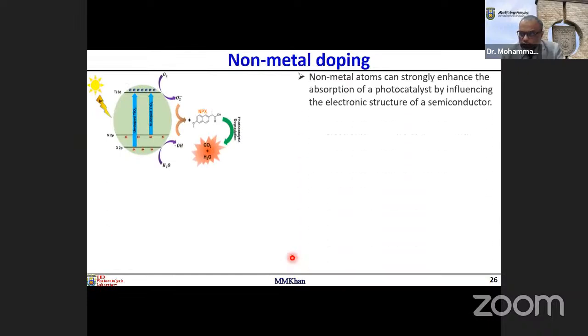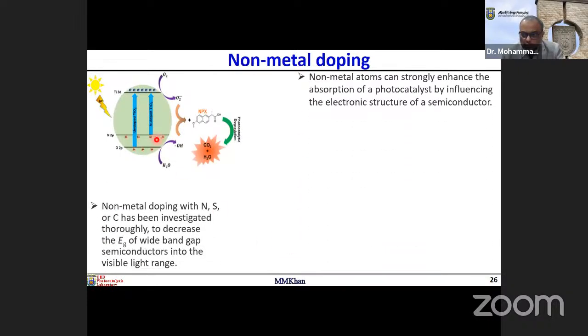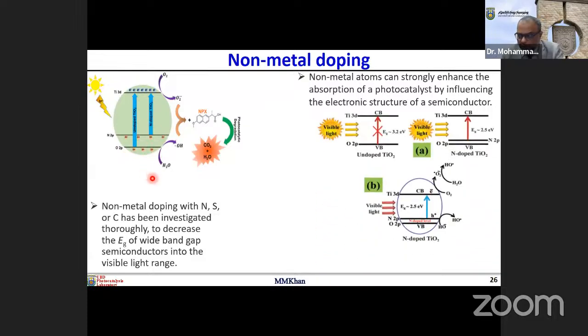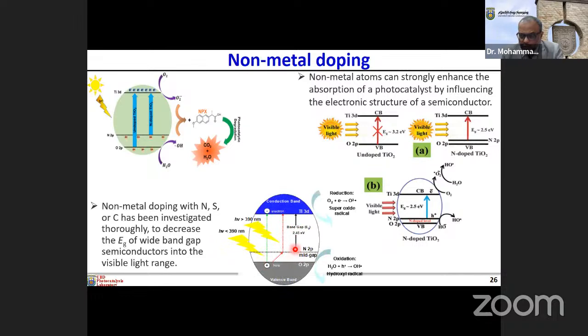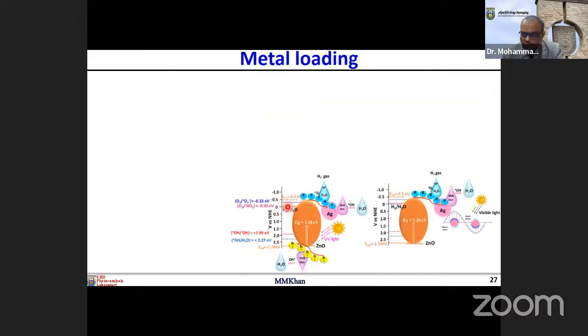Similarly, you can use non-metal doping. If you dope with a non-metal, the valence band especially will get affected, or it will move upward based on the dopant. You can see here that we can use different non-metals, maybe nitrogen or phosphorus or sulfur, and you can dope, and that will affect the valence band, and the band gap will be reduced a bit, and excitation of the electron from the valence band in the visible region is possible.